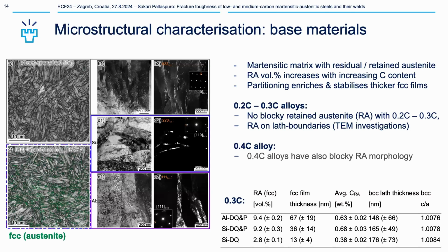First, to understand that these are lath martensitic microstructures with essentially film-like retained austenite. So we don't have this duplex type of structure where we have big grains of BCC and FCC, but the FCC is laminated between the martensitic laths, at least for the range of 0.2 to 0.3 carbon steels. Already with 0.4 carbon alloys, we start to get also blocky morphology of retained austenite, so larger globular particles of high carbon metastable austenite which will then under strain turn into very brittle martensite.